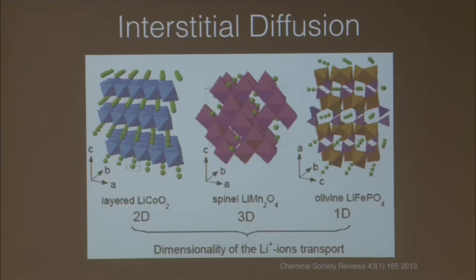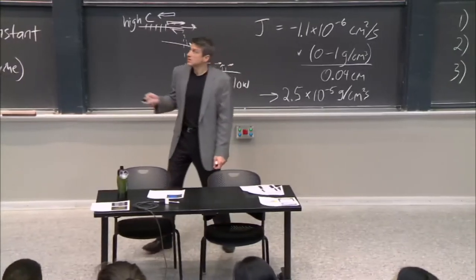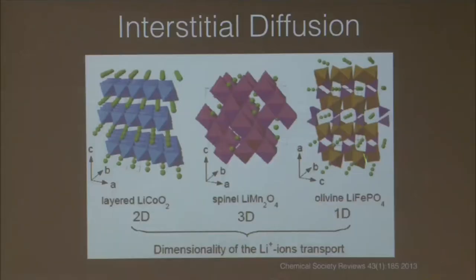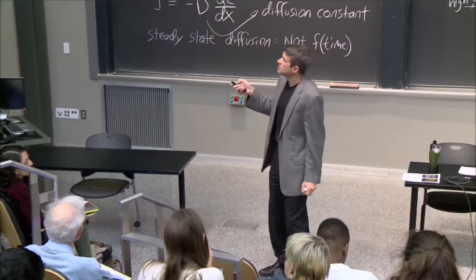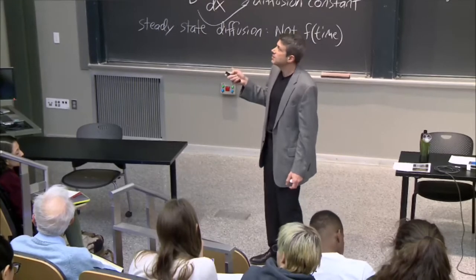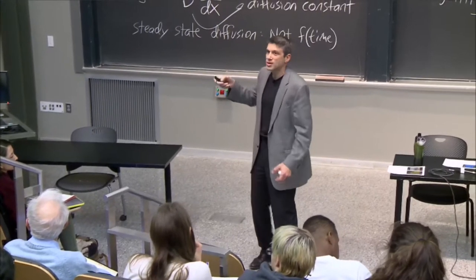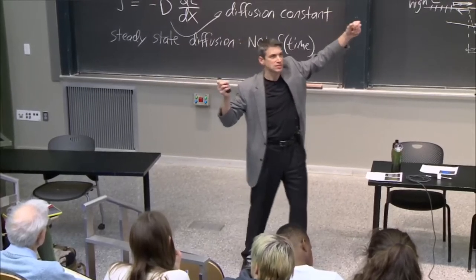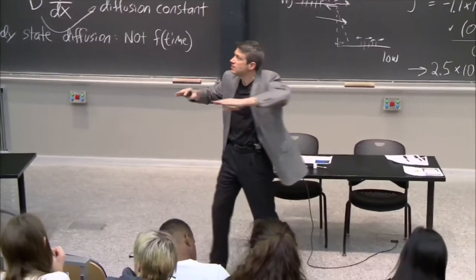What is the activation energy for a lithium atom in a given material? Does it take a 1D path? It turns out these can be extremely efficient — look at those, they're practically holes, they're lines in the lithium iron phosphate. That's a really nice cathode material because you've got these channels, these high conduction highways. But then maybe you need 3D voids so it can choose more paths, or maybe a layered structure where they have 2D planes to travel through.